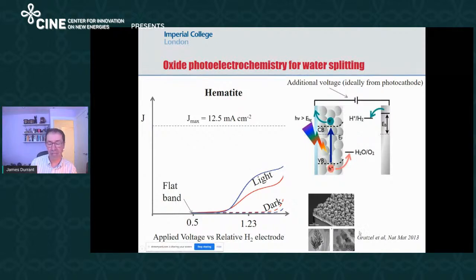potential in the light. Essentially, you need to apply a potential positive of flat band, where flat band corresponds to when there's no band bending at the surface. But in principle, if you could apply a potential of 0.5 volts, you turn on the band bending at the surface, and you absorb enough photons by hematite to generate 12.5 milliamps per square centimeter of current. And so that would be the ideal current voltage curve for hematite.